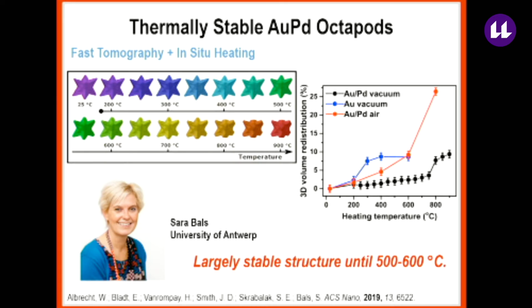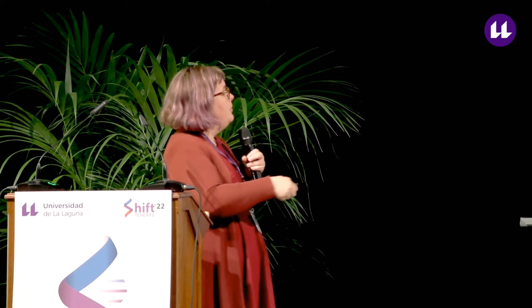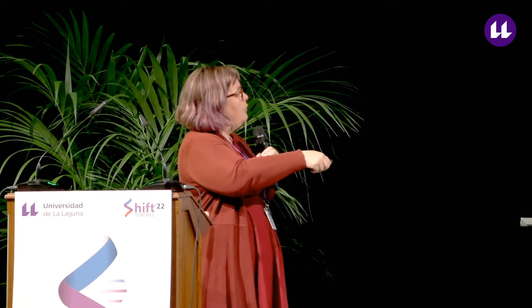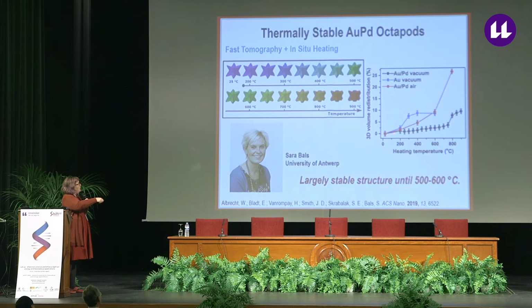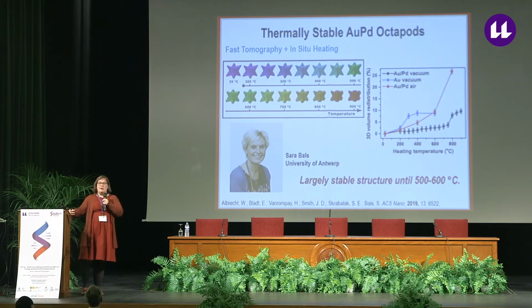And this contrasts with when you're just looking at the all gold octopods of the same size. A plot of those results is shown here in the blue curve, and there's a large volume redistribution between 200 and 300 degrees. So the addition of palladium is definitely stabilizing these nanocrystals.